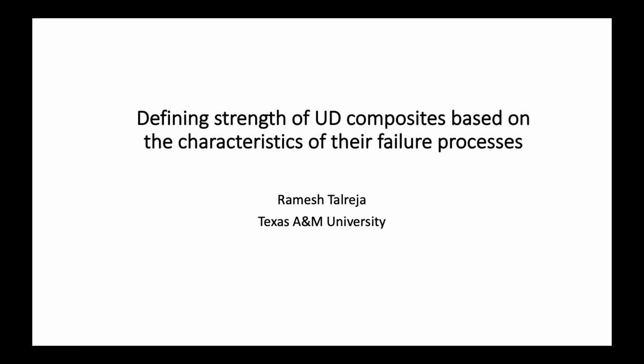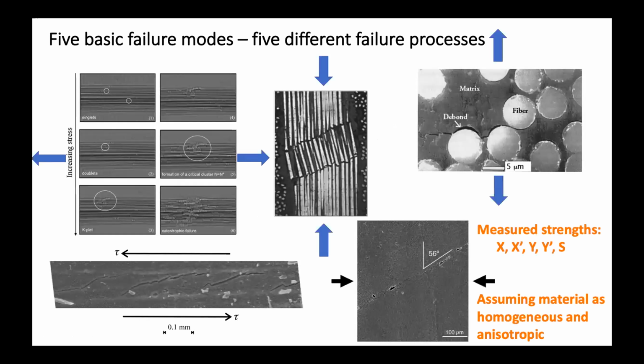So I'll go to the 2 slides that I have. As I say, a picture speaks 1,000 words. So what I have done here is to take 5 typical pictures of how observations of failure mechanisms appear when you take a unidirectional composite and load it in 5 basic modes. So you're looking at tensile mode in the axial direction, compression loading in the axial direction, tensile in the transverse direction, compressive in the transverse direction, and in-plane shear.